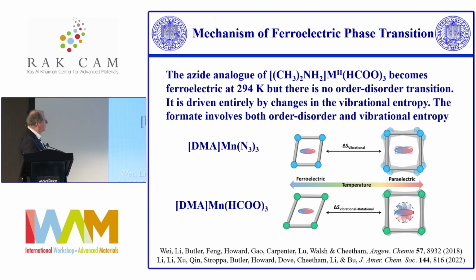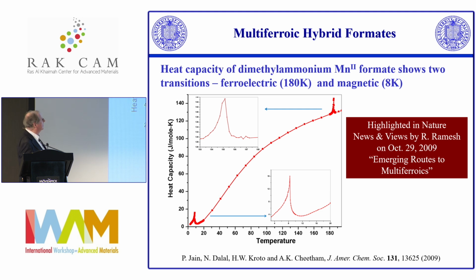So the next thing that we did, immediately following really the discovery of the ferroelectric ordering, I'd done a lot of work with CNR Rao, who's on our board and people have mentioned, I did a lot of work in collaboration with CNR on multiferroic materials. These are materials that, for example, order both as a ferroelectric and also as, say, a ferromagnet. And these are very rare animals. And at the time, all the known examples of multiferroics were systems where the ferroelectricity was driven by off-center displacements of cations, like you have in lead titanate and bismuth manganate, which is the classic.